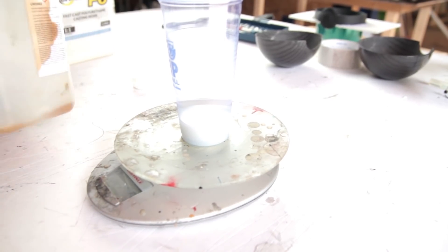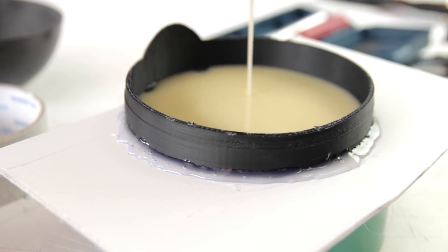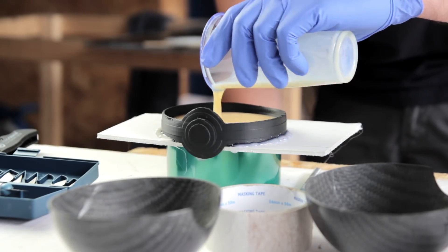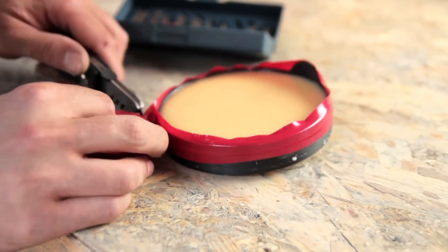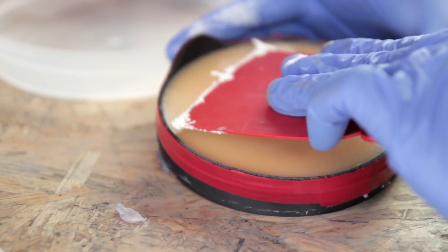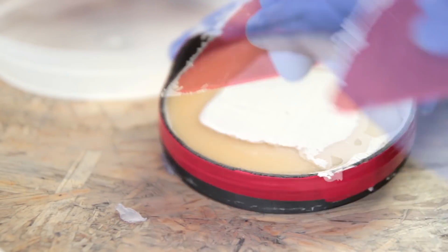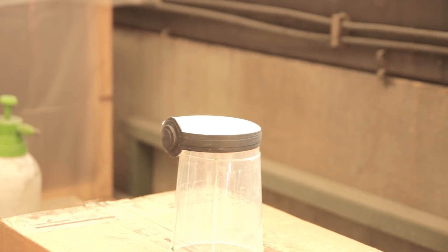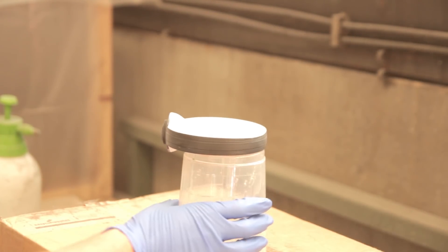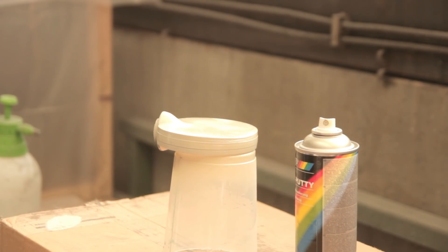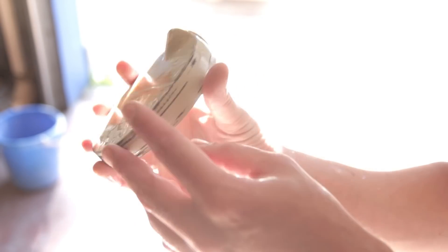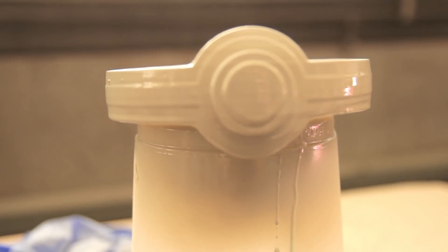Here is the Fastcast polyurethane resin I'm using, the P6. Easy Composites sells a range of five different polyurethanes with different stiffnesses and flexibilities. This one is good because it cures quite rapidly, after around 30 minutes. I did the first pour just to see if I had no leaks, because that would be horrible to pour 300 or 400 grams and see it dripping all over the floor. Then you still have some bubbles or shrinkage, which is why I used some fillers, and also the parts just behind the button, because this shape will have a better reflection of the light coming from the back.